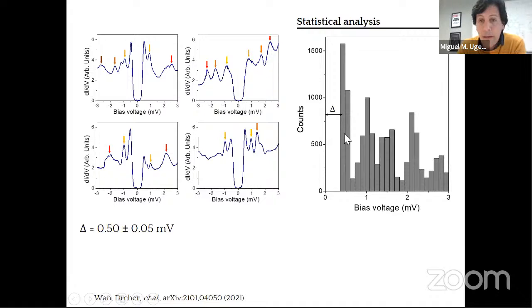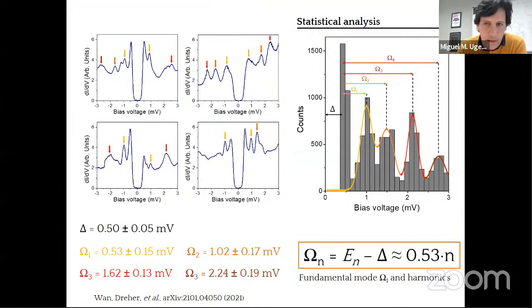So apart from the coherence peak gaps, there are another 4 peaks that you see in the statistical analysis in the histogram, and we can fit all these peaks and show that we find 4 different satellites at these energies: 0.5, 1, 1.6, and 2.2. Given the energies at which we find these satellite peaks, we attribute these 4 peaks to the existence of a fundamental mode, omega-1, as we call it here. We believe that what we are seeing is a fundamental mode followed by some harmonics that I will show you in a second. So they all follow this repetition rate, right?